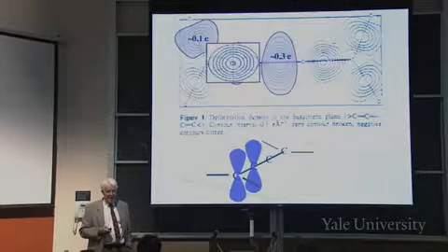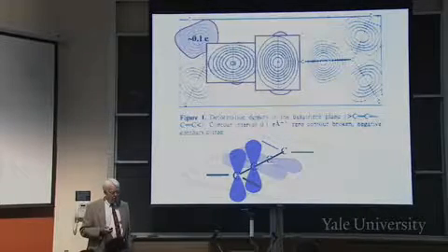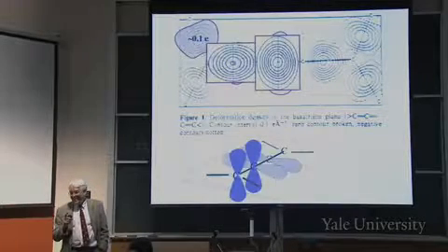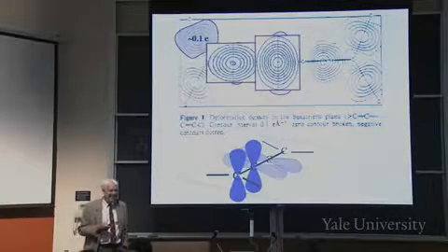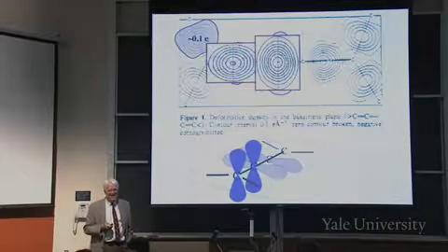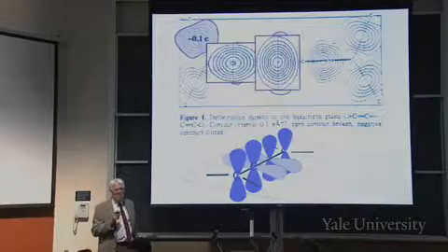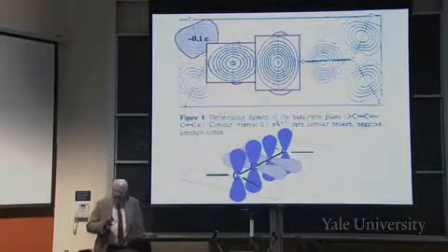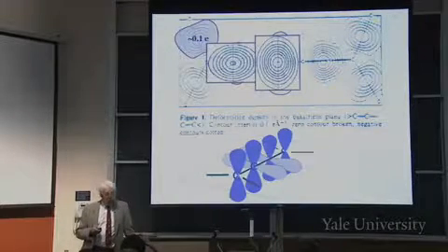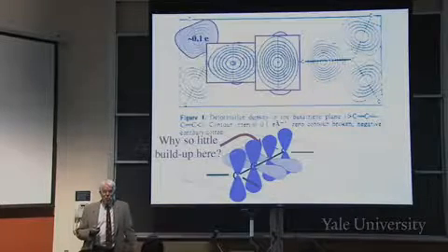How about the next one? If we slice it and turn it, it's also oval in cross section, but perpendicular. Right? What do you expect the next one would look like? It's symmetrical. It'll look like the first one again. But here's something interesting. That cross section of the middle one showed the deformation due to the pink, but not the deformation showing due to those neighboring blue ones.